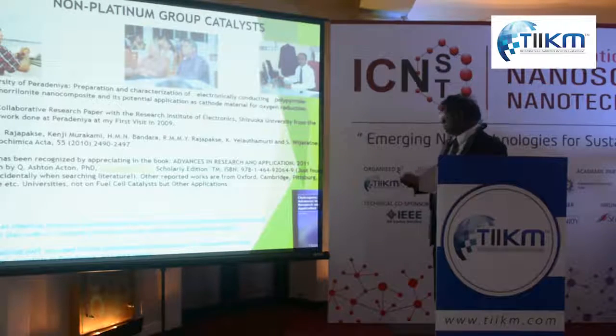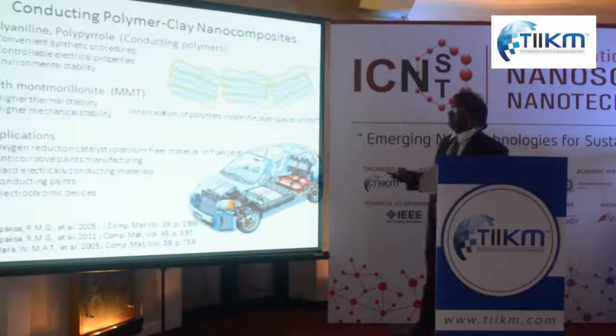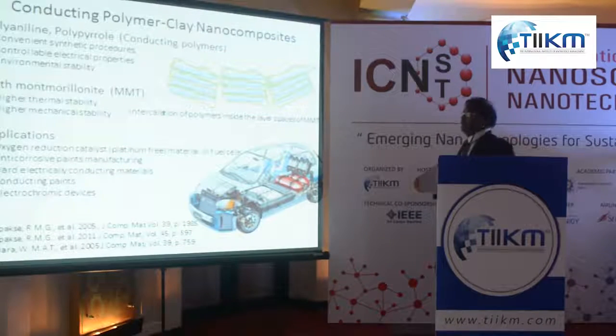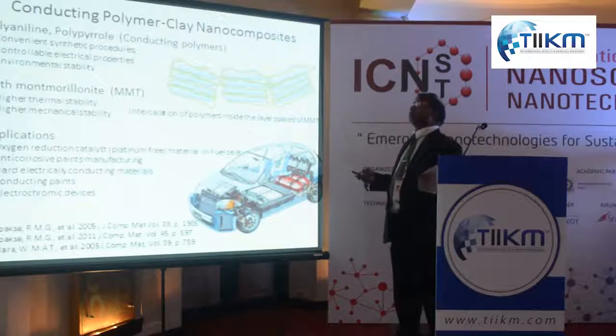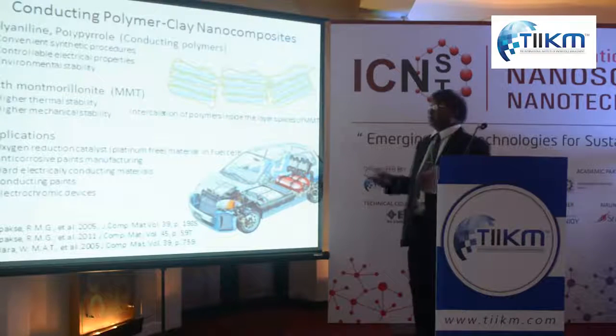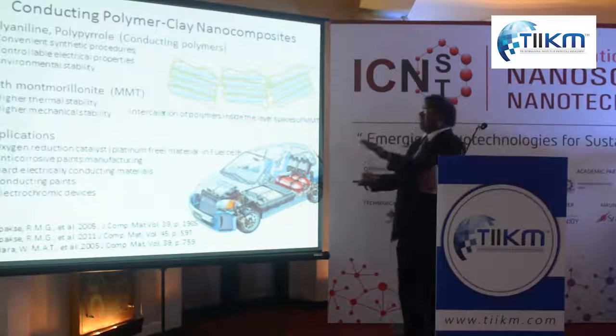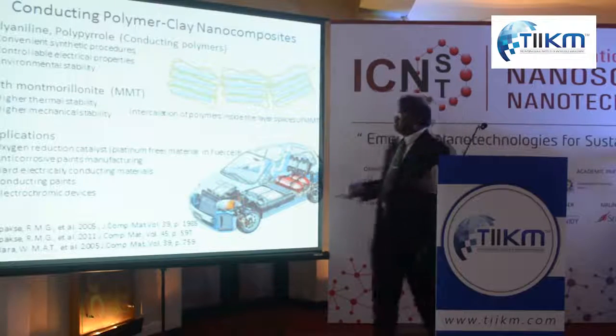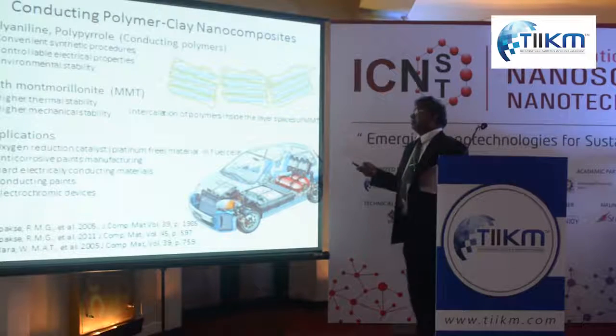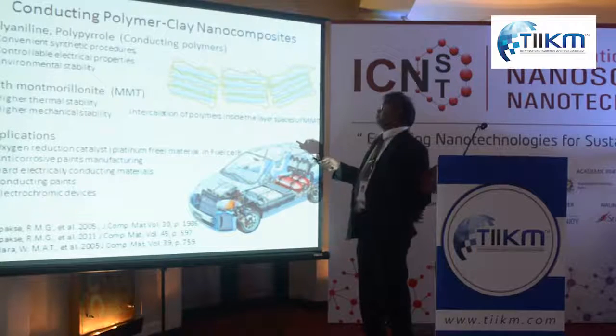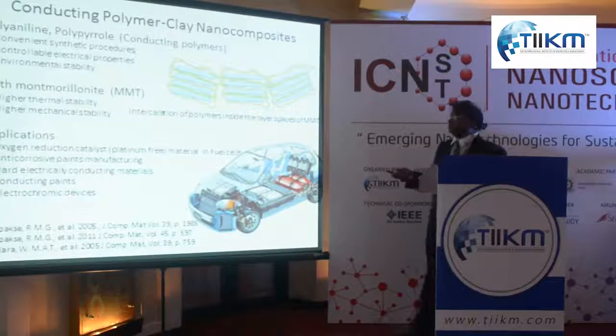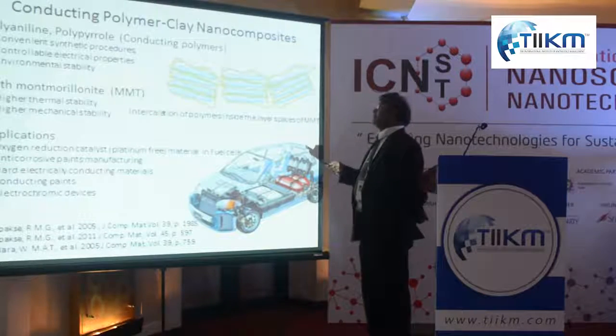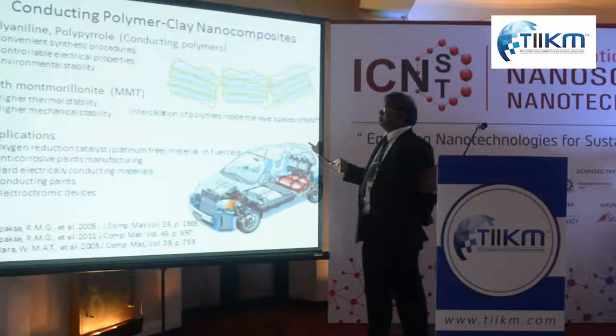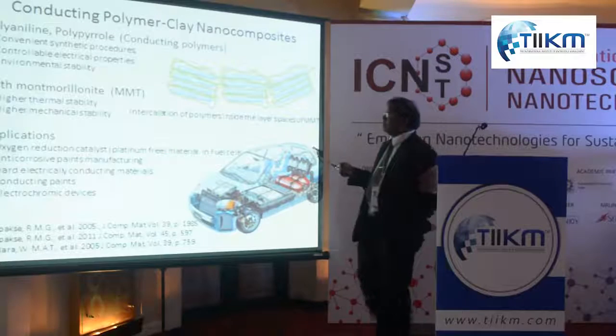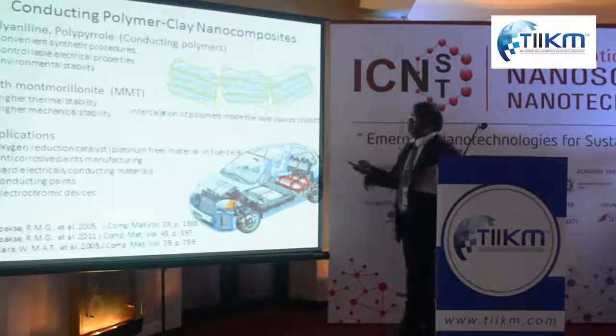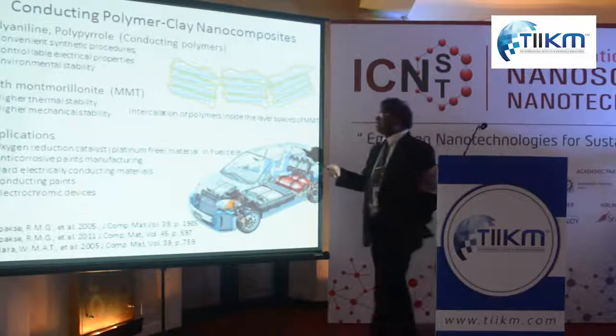What we did was we simply polymerized monomers like aniline and pyrrole. You know that when you polymerize them, you can convert them to an electronically conducting form of polymer in the presence of montmorillonite. As you know, clay has a layered structure. So what we did was very simple. These layers in the montmorillonite structure are negatively charged due to isomorphous substitution, where higher valent cations are substituted by lower valent ones, so that overall you have more negative charge. To counterbalance this negative charge, you have simple ions like hydrated sodium and calcium ions in the interlayer spaces. So these are exchangeable.